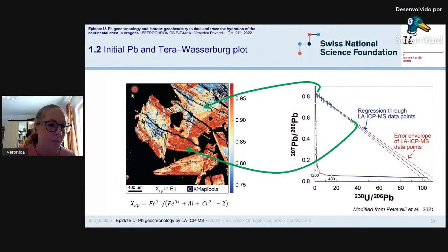This is a chemical map, so the black is quartz and everything else is epidote. And basically you see the spatial variability in iron to aluminum ratios. This sample doesn't contain chromium, just for you to know. This is actually by microprobe also. What you see here is that the variability in major elements, which are iron and aluminum, is quite high in this epidote sample. And variability in major elements can reflect variability in trace elements, such as uranium and lead. So ideally, to date epidote, we would like to use an in situ technique that samples small volumes, such as laser ablation inductively coupled plasma mass spectrometry, or LA-ICP-MS.